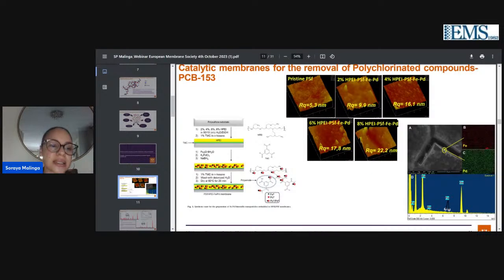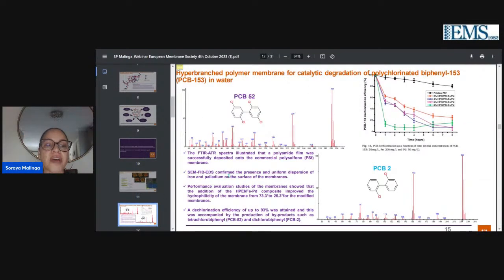Our analysis also showed that when we increased the HPEI, we saw that this had a drastic effect on the surface roughness of our membrane. For the final application, we targeted PCB 153. Our LC-MS studies did show that we have degraded it into other compounds, which were PCB 52 and PCB 2.